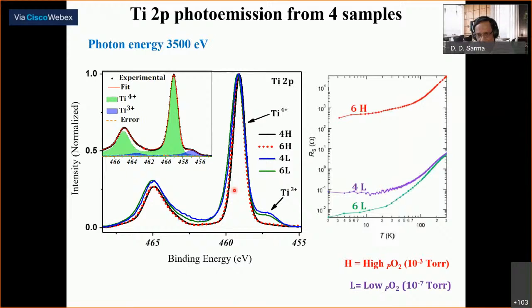But it is not this single signal. I see that my metallic signals also have this bump at lower binding energy, which is because of the titanium 3+ state. The titanium 3+ state tells me that there's one electron in the conduction band of titanium 3d. That tells me this is the one that is making the system metallic. And so now what I can do is to look at the intensity of this, normalized by this titanium 4+ signal, and look at how it varies with the photon energy.